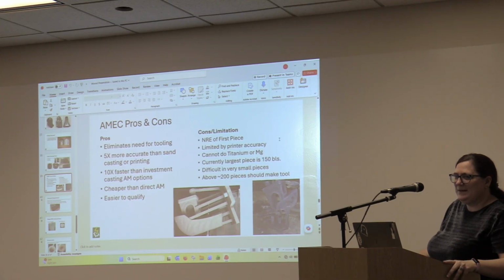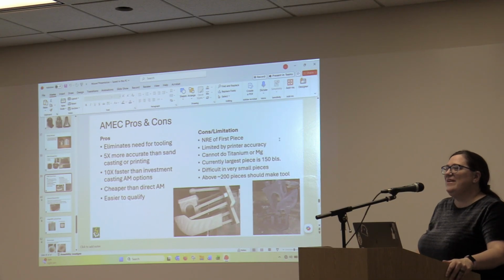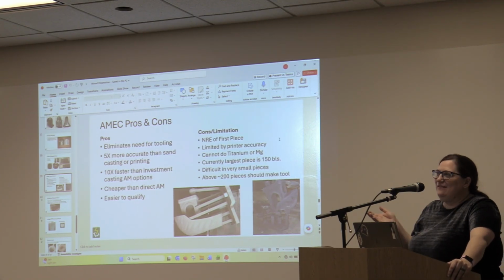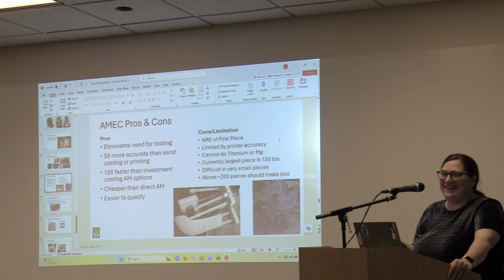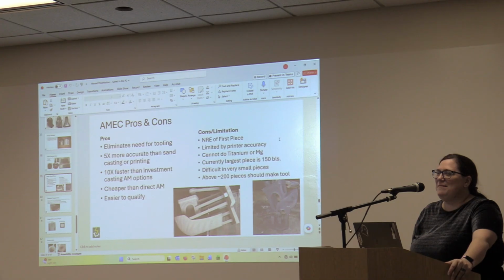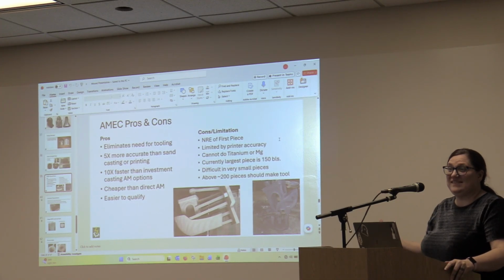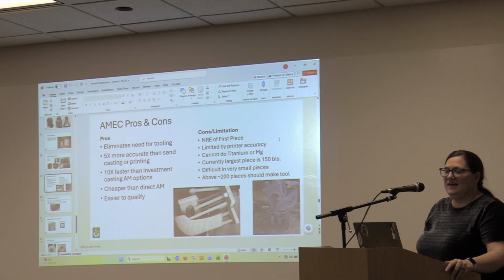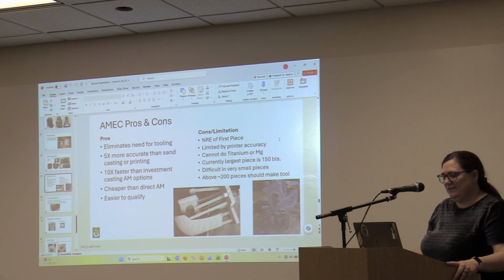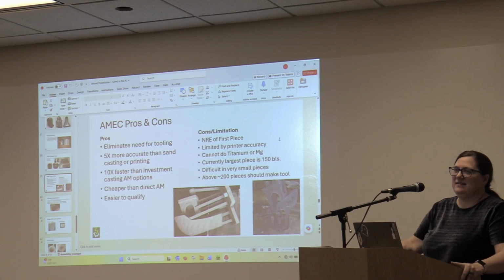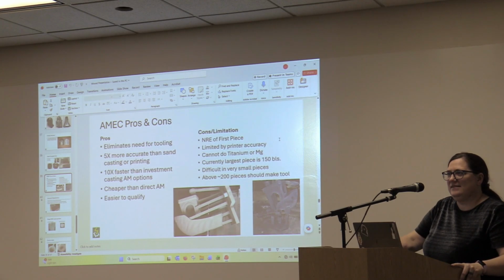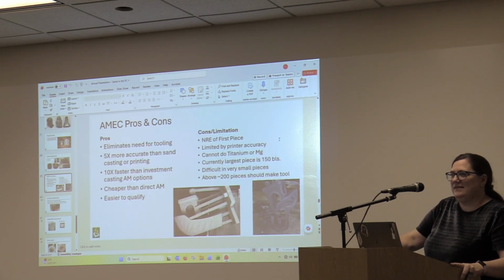And what's the longest process within that? Well, for lost foam, the longest step is drying. And then in AMEC, it's kind of a tie between the printing process itself and drying. And that's the problem with investment casting too, you're putting multiple layers on. You may dip 15 times, and each one of those you have to dry, and that shell has to be dried before you can pour metal into it, because you have to preheat it. If it's wet, you're going to have steam and all kinds of explosions.